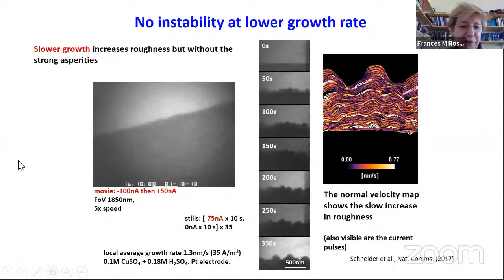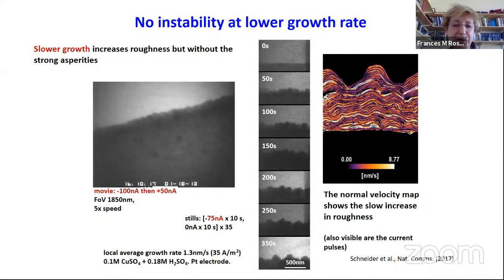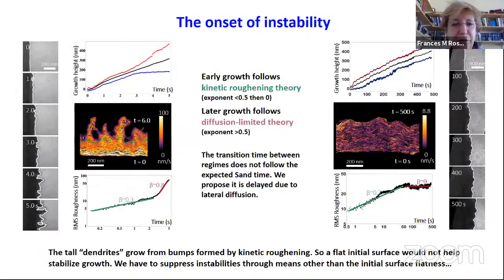If we grow more slowly, the movie is actually much less interesting, because really not a whole lot happens. You can see it's growing. You can see this, and now the movie is just repeating itself. You can see just the growth of the copper front, and you can see that there isn't much in the way of development of dendritic structures here. Okay, so what can we do with these things?